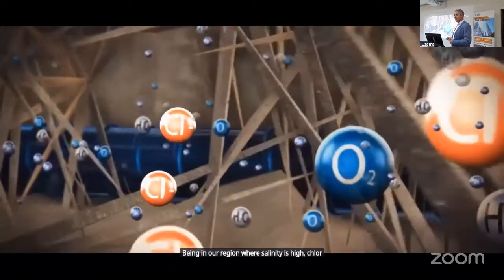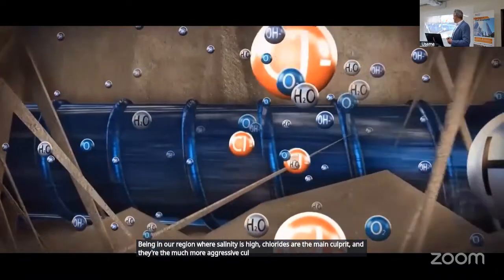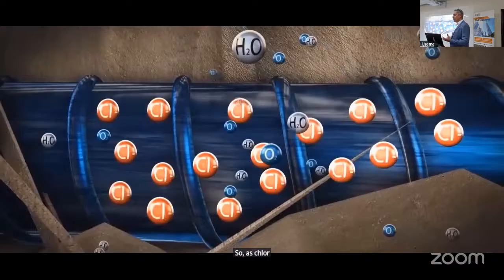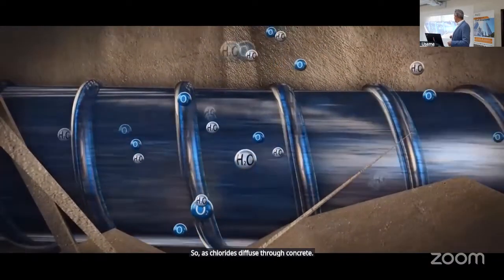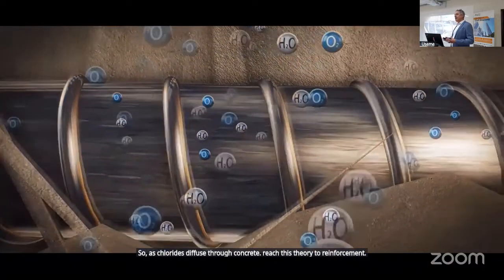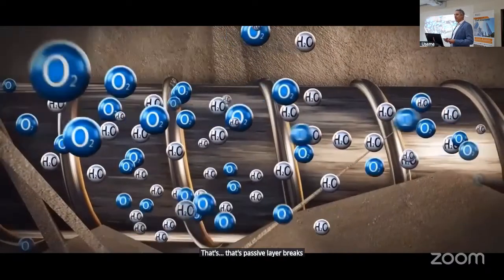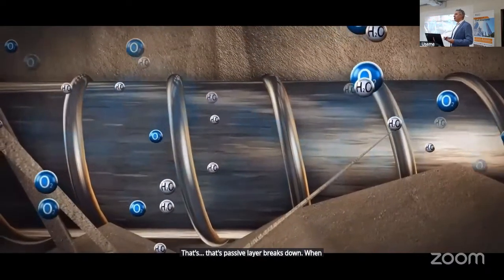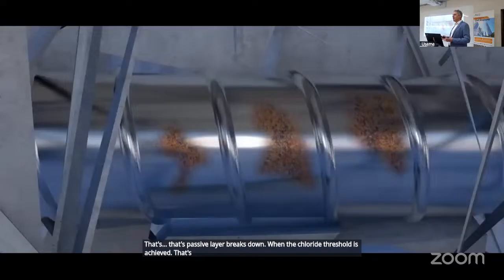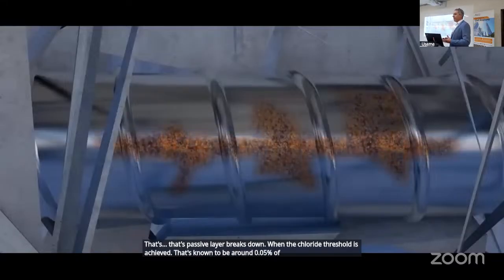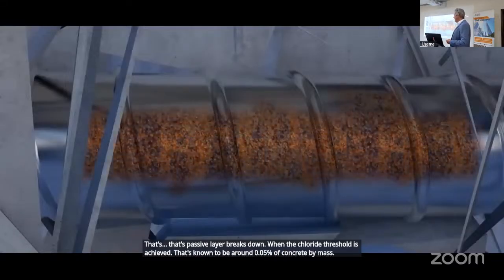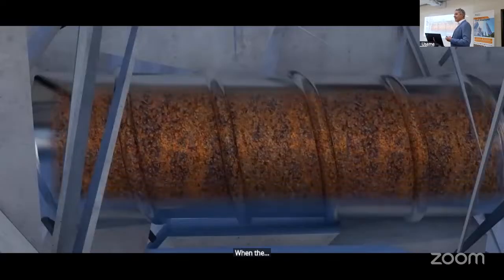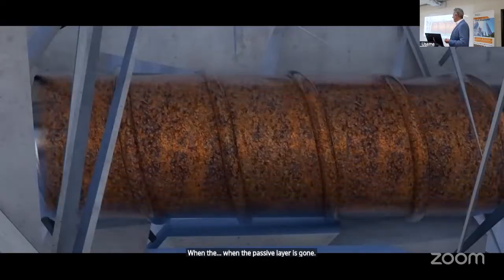The problem happens with the breakdown of that passive layer, which occurs due to carbonation, but being in our region where salinity is high, chlorides are the main culprit, and they're the much more aggressive culprit. So as chlorides diffuse through concrete and reach the steel reinforcement, that passive layer breaks down when the chloride threshold is achieved. That's known to be around 0.05% of concrete by mass. When the passive layer is gone, corrosion starts.